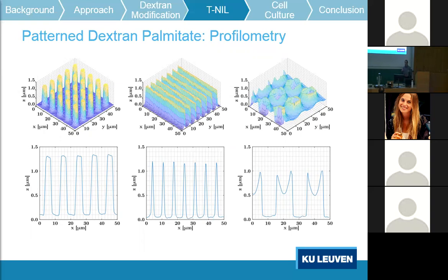So effectively, because I have such a wide range of sizes of structures on my material, it becomes difficult to flow the material into the larger structures at the same rate as they would in the smaller structures, for example, here. So the issue here is that the material isn't completely filling the cavity or void in the stamp. And of course, this could be optimized in a way by altering some of the parameters of the procedure, such as increasing the pressure, increasing the time at which the procedure is carried out, and so on.